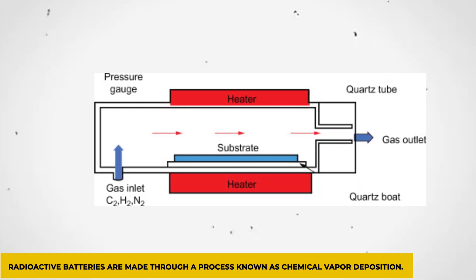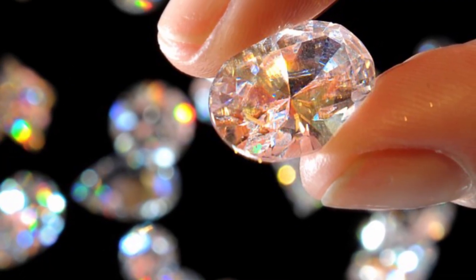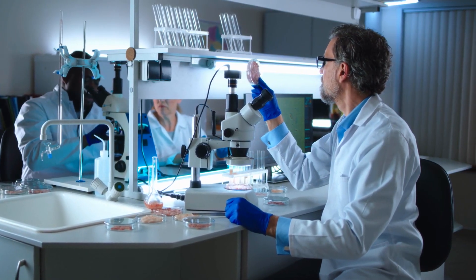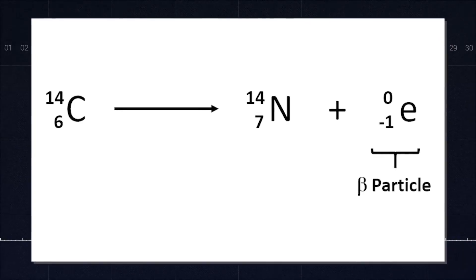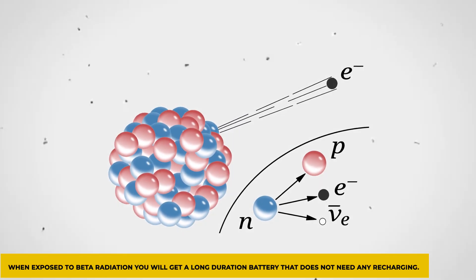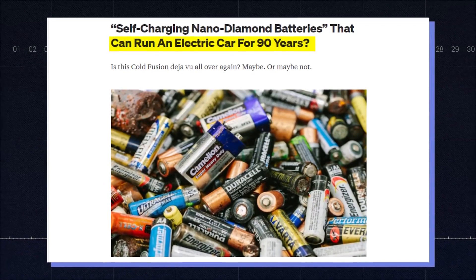Polycrystalline diamond, or PCD. Radioactive batteries are made through a process known as chemical vapor deposition, which is the process often used for making artificial diamonds. The researchers modified the process to grow radioactive diamonds by using radioactive methane containing the radioactive isotope carbon-14, which can be harvested from irradiated reactor graphite blocks. These diamonds act as both a radioactive source and a semiconductor. When exposed to beta radiation, you get a long-duration battery that does not need any recharging, as the nuclear waste inside fuels its interior over and over again.